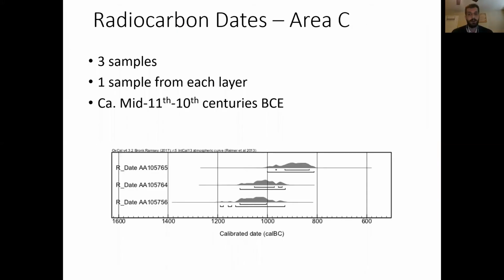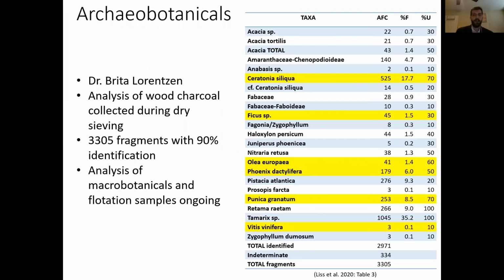We collected 3 radiocarbon samples from the slag mound excavation, 1 from each of the identified layers that I mentioned. Generally, the dates fit with the mid-11th to 10th centuries BCE, with that bottom thick accumulation of crushed slag being in the mid-11th. This then fits with the idea that that stone structure was also constructed in the mid-11th century BCE, suggesting that this site had a fairly rapid establishment from its outset, with immediate large-scale copper production and a large stone structure. Along with the radiocarbon dates, we also did an archaeobotanical analysis.